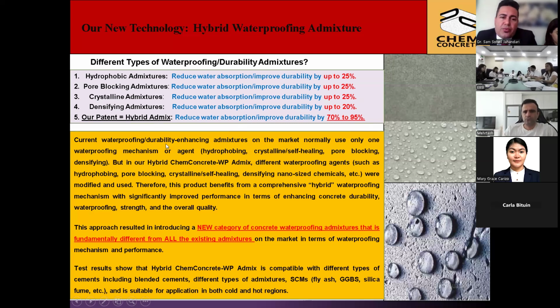So current waterproofing admixtures on the market normally use only one waterproofing mechanism or agent, like hydrophobing, crystalline, self-healing, pore blocking, or densifying. But in our ChemConcrete Hybrid Admixture, different waterproofing agents such as hydrophobing, pore blocking, self-healing, densifying nanosized chemicals, and so on were modified and used. That's why this product benefits from a more comprehensive hybrid waterproofing mechanism with significantly improved performance in terms of enhancing concrete durability, strength, waterproofing, and overall quality of concrete. And yeah, this approach resulted in introducing a new category of concrete waterproofing admixture that's fundamentally different from all the other existing admixtures on the market in terms of delivering a true waterproof and durable concrete.